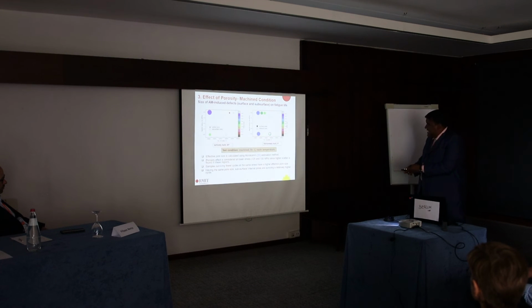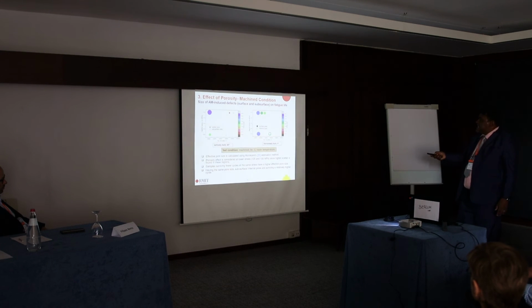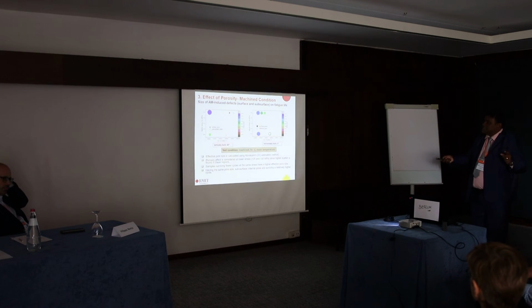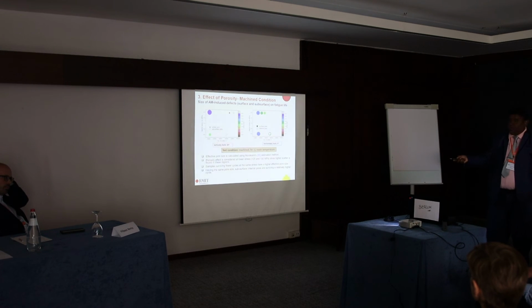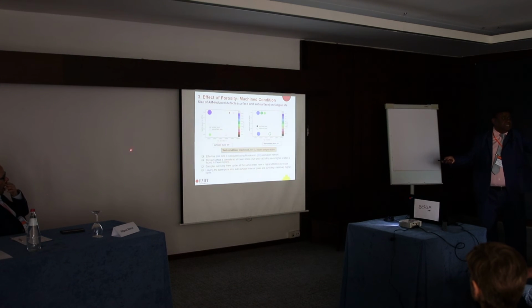Look at the thing clearly. If you have the same stress level, the pore size affects the fatigue life. The smaller the pore, the higher the fatigue life, right? However, there's a difference between the surface pores, which are solid circles, and the internal, subsurface pores, which are open circles. A subsurface pore is less critical, and that will allow you to get a much higher fatigue life compared to a pore on the surface of the same size.